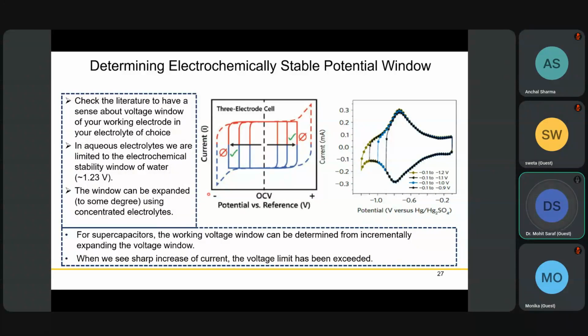If you see some kind of redox peak, then it is okay. But in the second cell, if that's not happening and you just see the sharp tail increasing, that means hydrogen evolution has started, so you have to stop from there. So that's the maximum I can go.